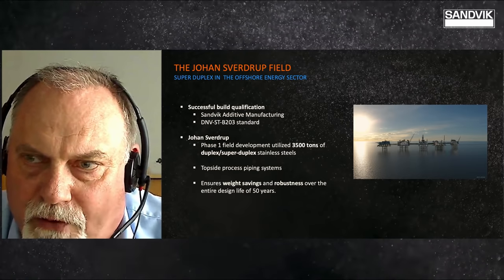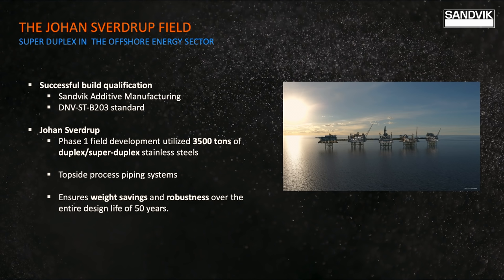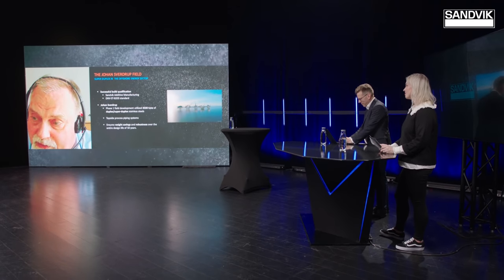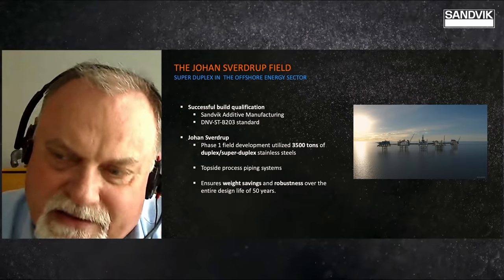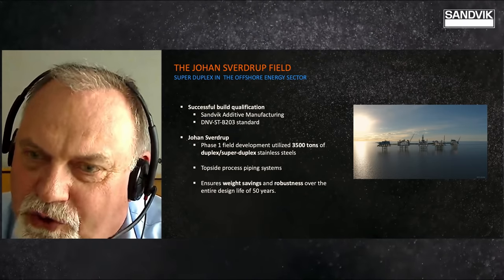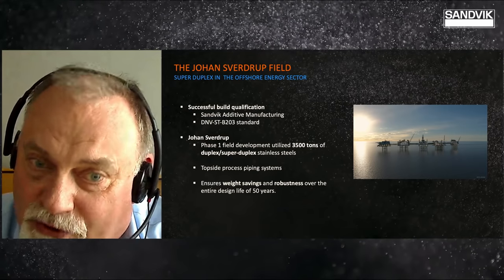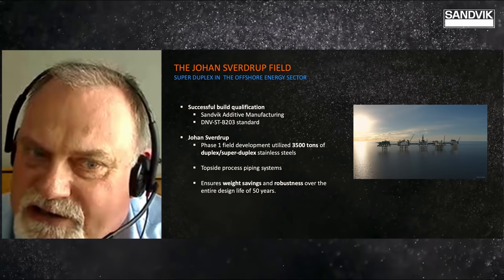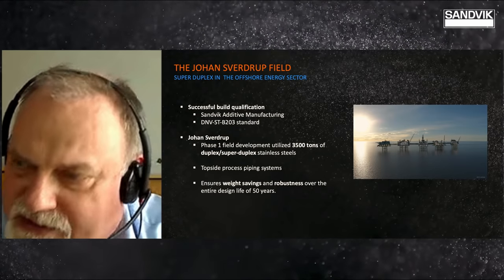And what we have also done together with Sandvik recently is a successful build qualification that was finalized with Sandvik following the recently published DNV-ST-B203 standard. And we saw excellent mechanical properties as well as corrosion properties, like demonstrated earlier in the webinar. And as a final example about the importance of super duplex, the recent Johan Sverdrup field development utilized as much as 3,500 tons of duplex and super duplex stainless steels, and only in the topside process piping system, to ensure weight savings and robustness over the entire design life of 50 years. I think that's all from me.